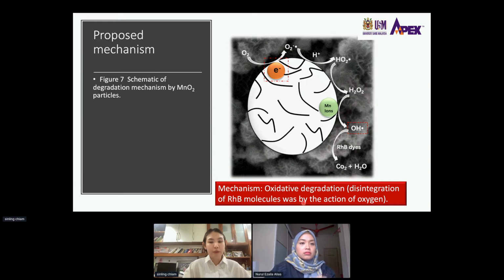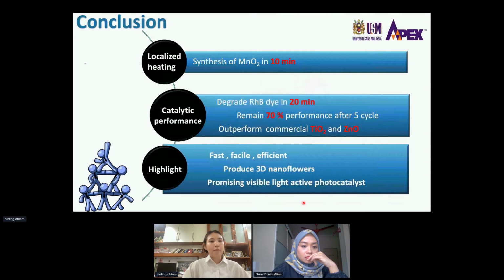So as a recap, this study shows the synthesis of manganese oxide using localized heating. The process only requires 10 minutes. Then the synthesized MnO2 is able to degrade the RhB dye in 20 minutes, where the performance is able to remain 70% after 5 cycles. And it also outperformed the commercial titanium oxide and zinc oxide.